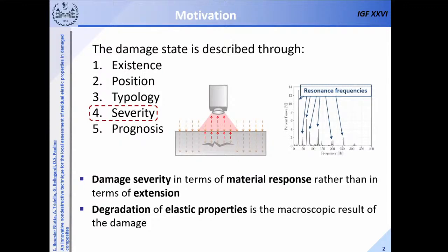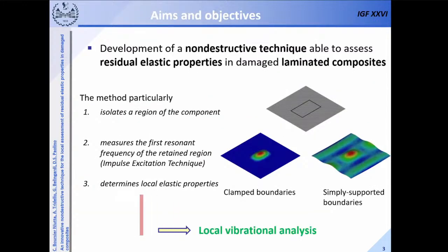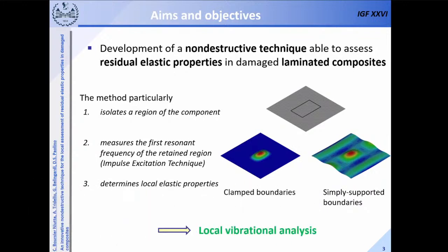These observations suggest the need of assessing the damage severity in terms of material response in presence of damage or flaws, rather than in terms of extension of the cracked area, as usually done in current non-destructive techniques. And the degradation of the elastic properties is the macroscopic result of the damage. So we aim at developing a non-destructive technique able to assess the residual elastic properties in damaged composites. And the method intends to isolate a region of the component by clamping the boundaries. And in this way, a specific mode can be excited, as you can see here in the figure. And from the measurement of the first resonant frequency, the elastic properties of the retained region can be assessed.